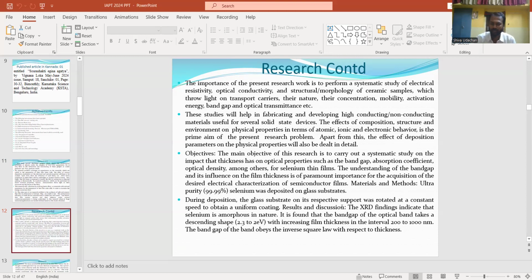Results and discussion of this research paper. The XRD findings indicate that selenium is amorphous in nature. It is found that the optical band gap decreases from 2.3 to 2 electron volts with increasing film thickness in the interval of 200 to 1000 nanometers. The band gap obeys the inverse square law with respect to thickness. Now moving to the next slide.